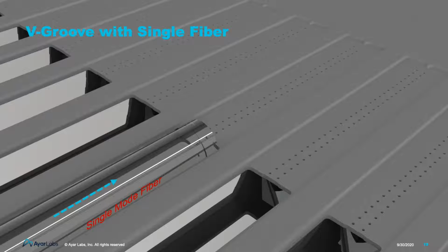Light propagating down the fiber is incident on the optical facet. Here I have shown the location of the optical facet for the adjoining Vgroove. However, this same structure exists at the end of each spot size converter. Now we can start to consider some material properties for the assembly. First, note that there is a slight gap between the optical fiber and the spot size converter. This gap, in fact the entire region, will be filled with an epoxy.